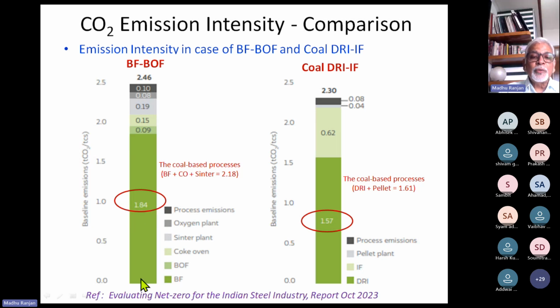So here, this is a cumulative sum of the contribution from blast furnace, from basic oxygen furnace, from coke oven, from sinter plant, oxygen plant, and process emissions. If we just try to see how much CO2 emission rate there is up to the iron making stage, we sum up the BF emissions, coke oven emissions, and sinter emissions. This adds up to 2.18 tons of CO2 per ton of crude steel. And the rest, that is the steel making part, is only around 0.28. So the major chunk in the blast furnace BOF route, the maximum CO2 generation, is up to the iron stage.